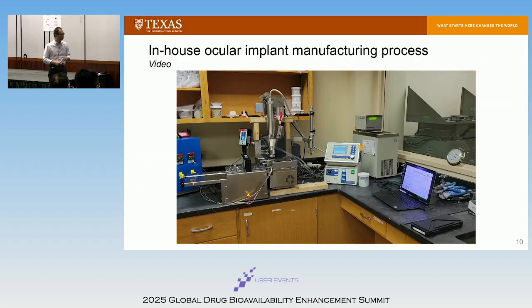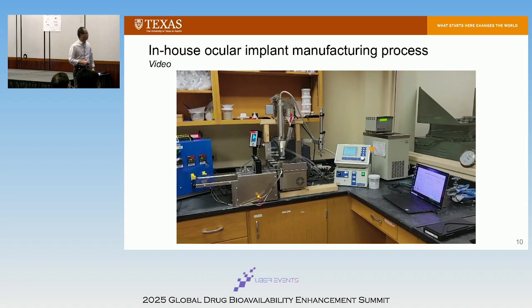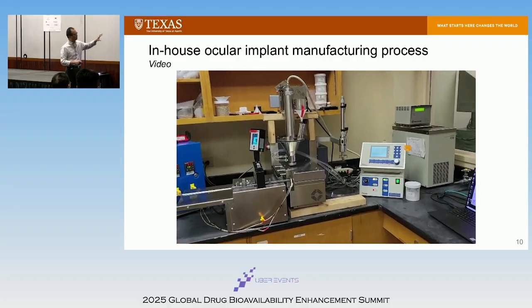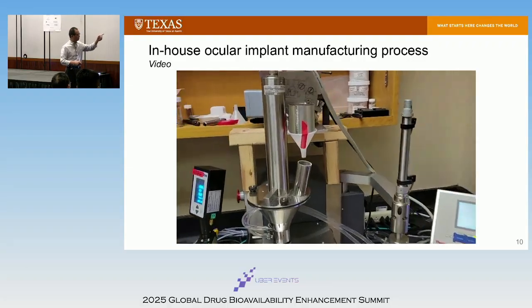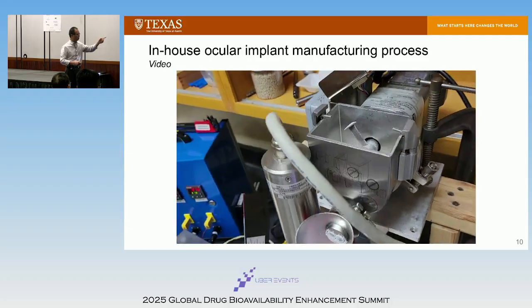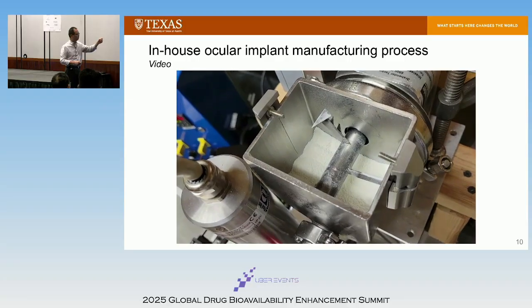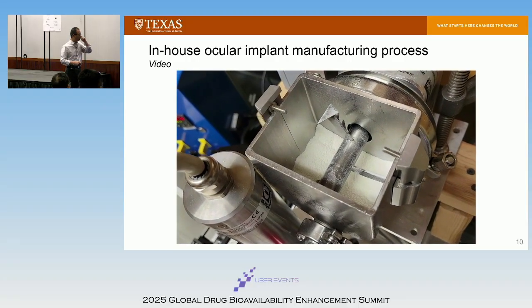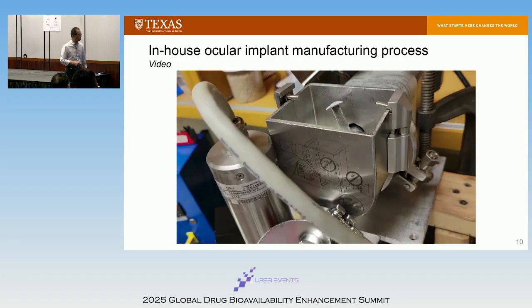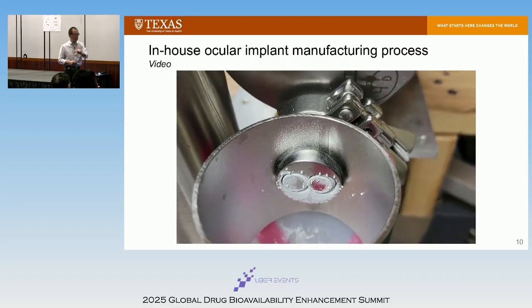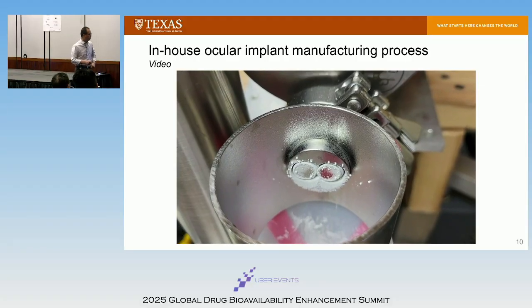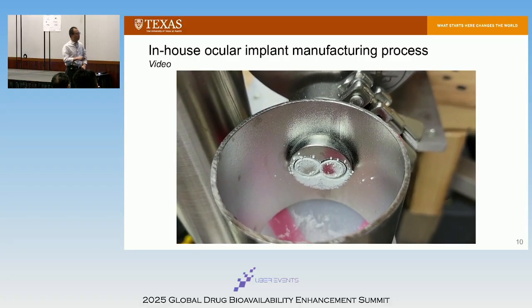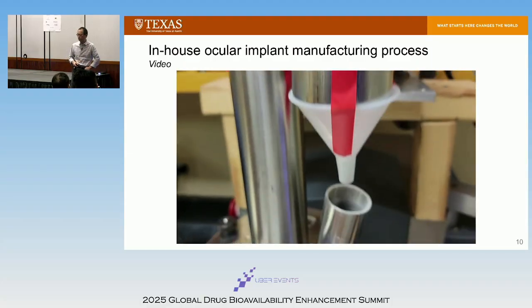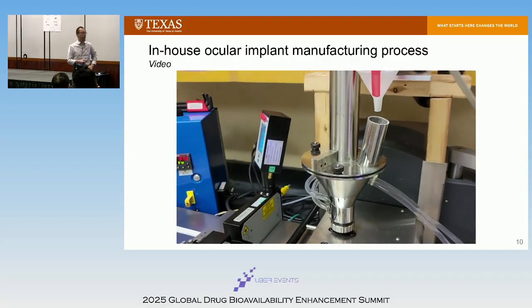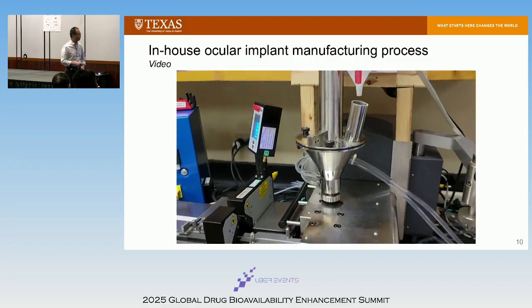So here's the video. Can you play this video? So this is actually the second step extrusion. We already made the granules. That's on the feeder on the top. Okay, we're using a Haake Mini Lab. We're running 10 grams per hour, very slow. The dose is very low. We can't feed everything at one time because PLGA has low Tg. If you feed too much, you're going to choke the feeder.